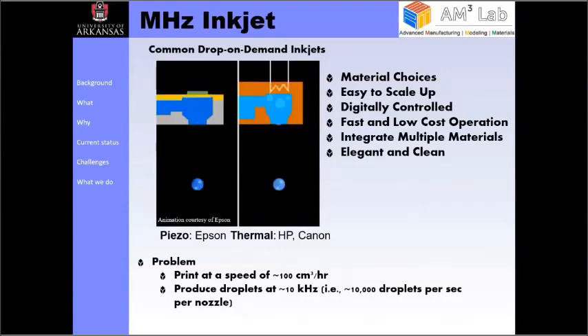So one of the problems with this inkjet technology is that you print at a speed of about 100 cubic centimeters per hour. It's a very slow process. If you want to print a 100 cubic centimeter cube, it's going to take an hour, which is not economical. And it produces droplets at about 10 kilohertz in terms of frequency, which means for every nozzle, and you can have an array of nozzles for each print head, you can have as many as 10,000 or even more nozzles, but each nozzle produces about 10,000 droplets every second.